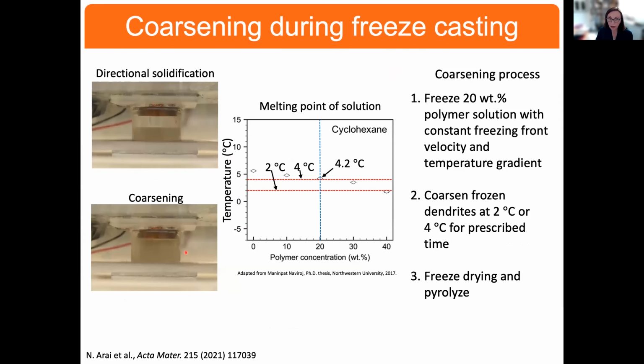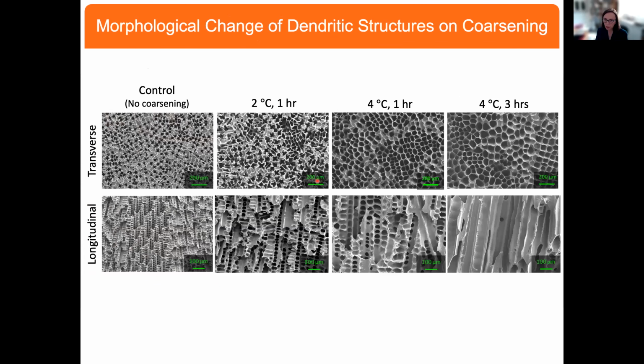There are other ways to do this as well, and that is to use coarsening. So we directionally solidify these materials, but then we sit them very close to the melting point of the solution. And in doing so, we can get the cyclohexane to coarsen in a way that it's going to impose that on the pre-ceramic polymer. So here's the coarsening process where we would freeze the material at constant freezing front velocity and temperature gradient. We've coarsened in this region and then would freeze dry and pyrolyze the material. And basically we're moving from, again, this highly dendritic structure to the honeycomb-like structure with cellular pores.